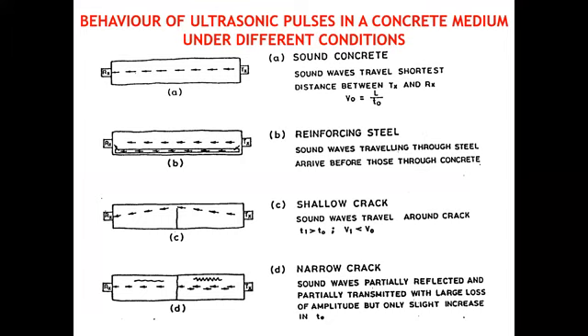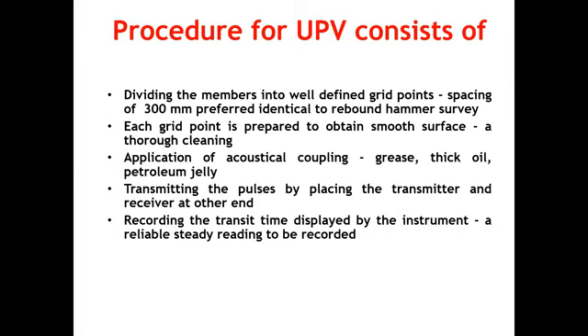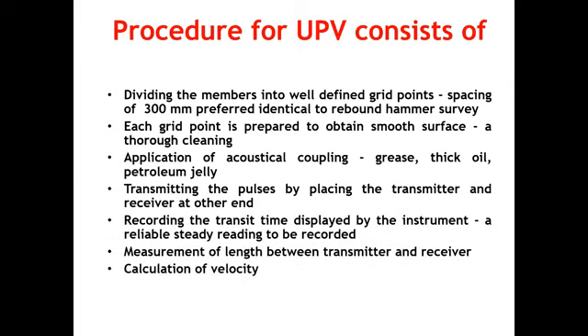The code gives you the spacing between the points: 300 millimeters center to center is a grid point. We are supposed to have it, and then take the reading. We normally use acoustic coupling, and normally we go with grease. Of course, the manufacturer also gives you acoustic coupling, which is very expensive, but normally you can go with the grease. The whole purpose is that we don't want any gap or void between the concrete surface and the transducer, because however much grinding we do, we cannot make the surface exactly flat. So we need to use some gel, which could be a petroleum gel, so that the contact is proper. One transducer transmits the pulse, the other receives it, and then we can calculate the velocity.